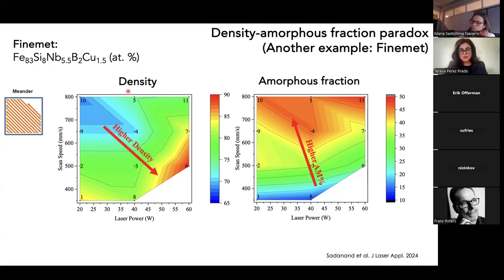And if we plot within this region the density and the amorphous fraction with respect to scan speed and laser power, again we obtain this inverse, or opposite, variation of these two variables. And again, the maximum amorphous fractions that we could get were about 50%. So this is clearly a problem that we need to solve somehow.